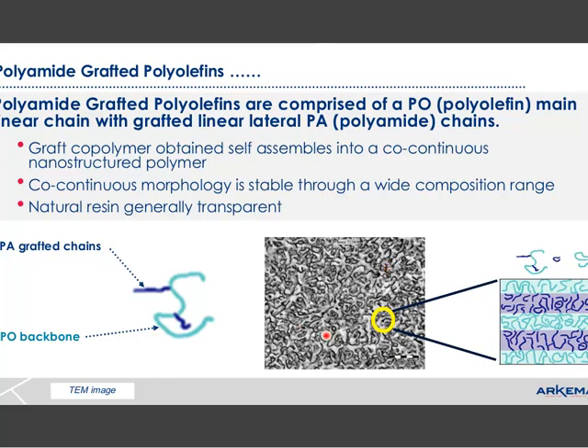Looking over here at a TEM image of one of these grafted copolymers, we see phase separation, where the matrix itself is the polyolefin, and what look like small sea worm-like creatures in this background are the polyamides segregating. It's a co-continuous phase, and this morphology provides a very useful set of performance characteristics for multiple applications, including wire and cable. The natural resin itself is transparent because the size of the structure is extremely small.